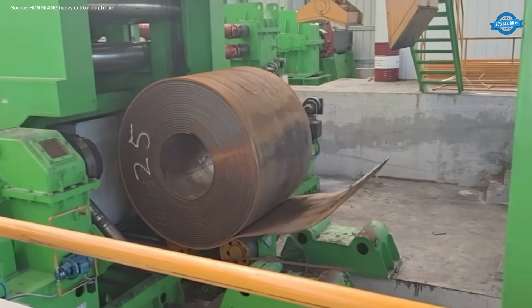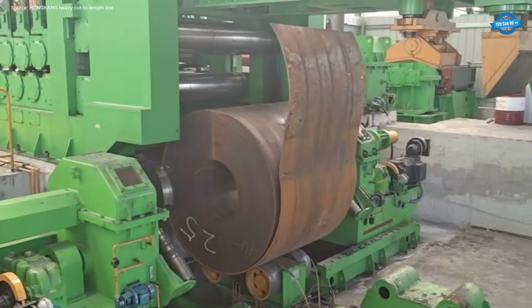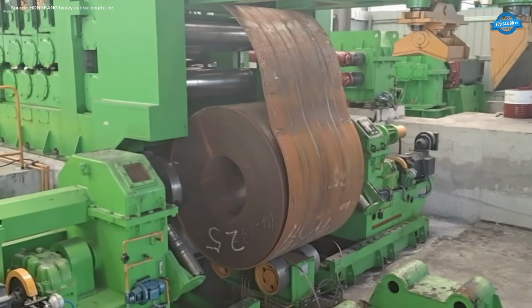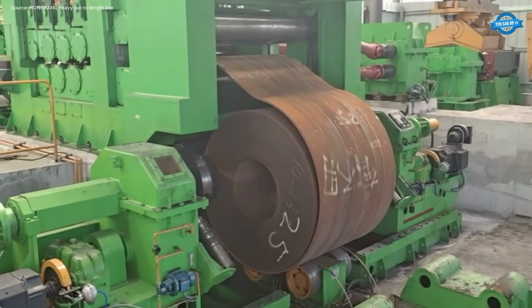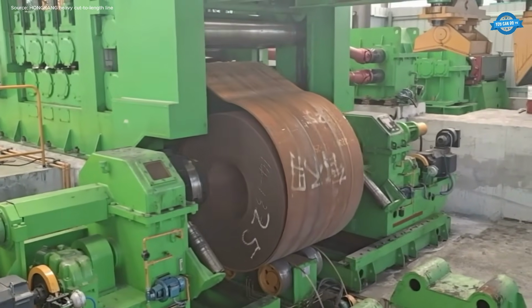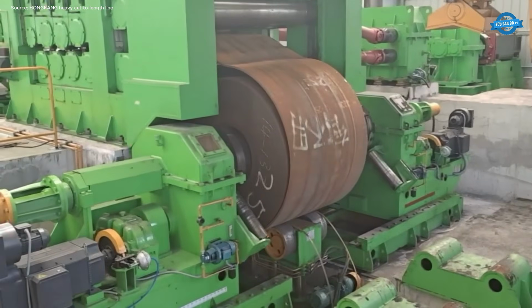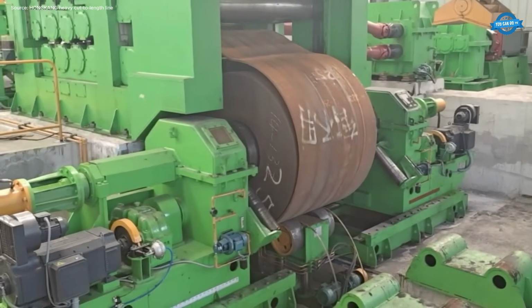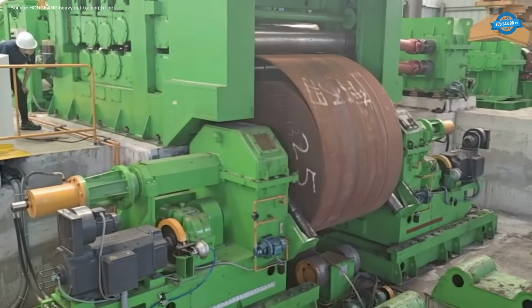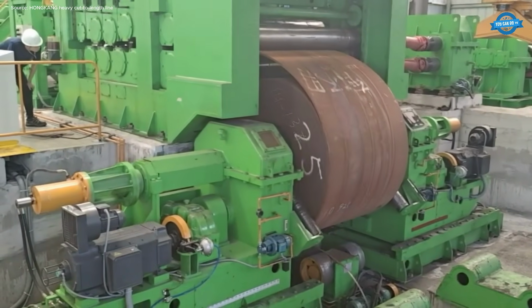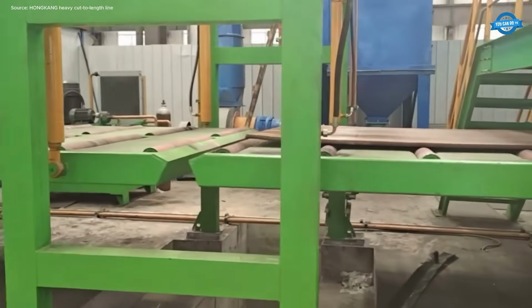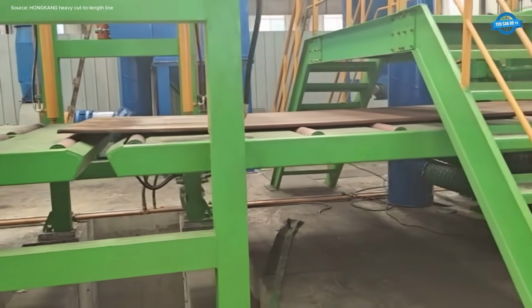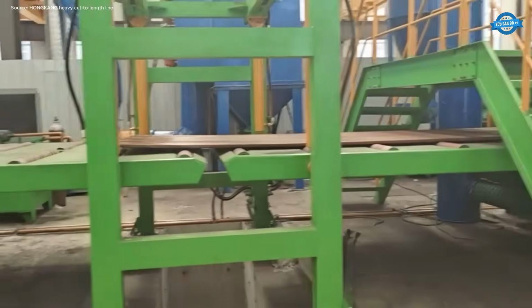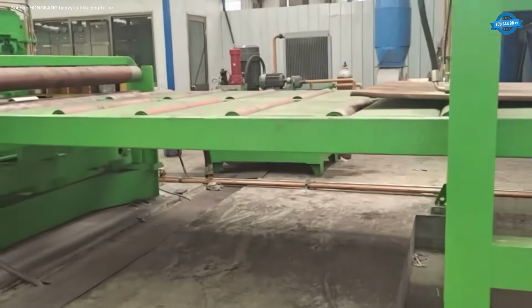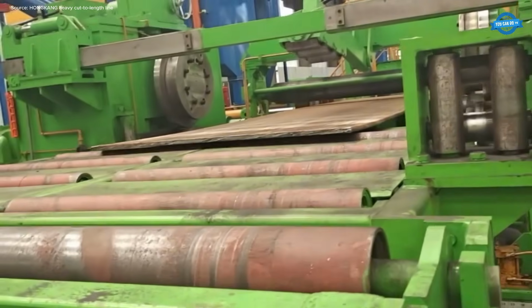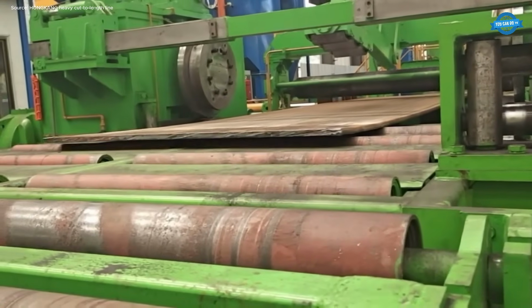The process of transforming a 25 mm thick steel coil into flat steel plates using a cut-to-length (CTL) line involves multiple precision steps. First, the steel coil is mounted onto an uncoiler, which securely holds and gradually unrolls the heavy coil. As the steel uncoils, it passes through a straightener or leveler, where powerful pinch rolls and leveling rollers remove internal stresses and correct any coil set or curvature. This is critical for achieving flat, usable plates.